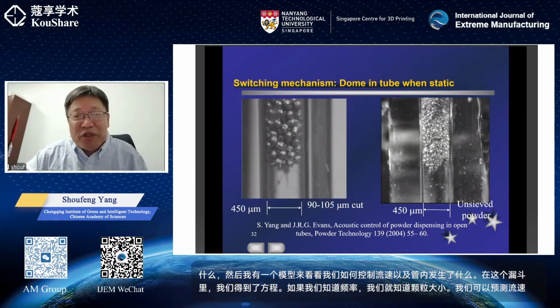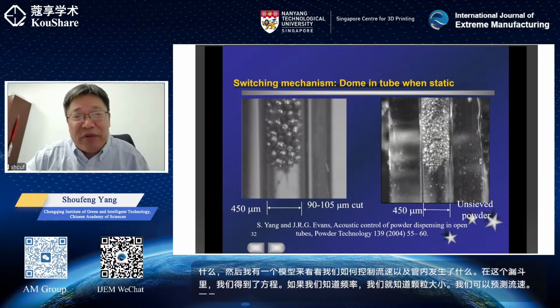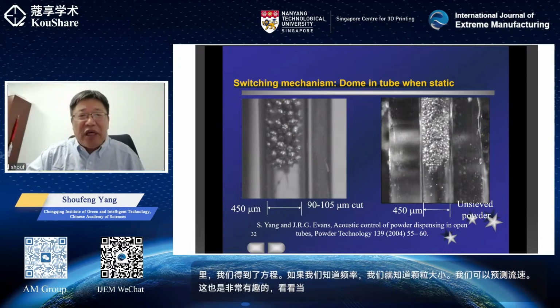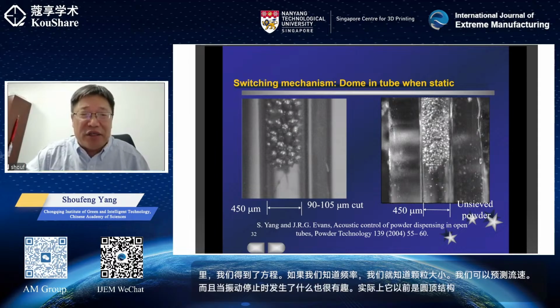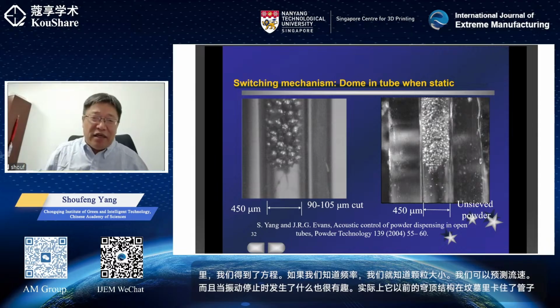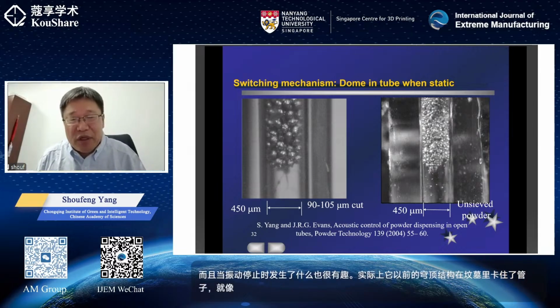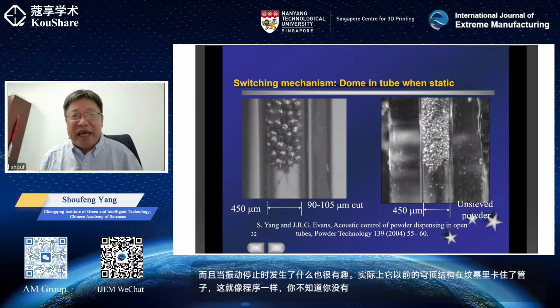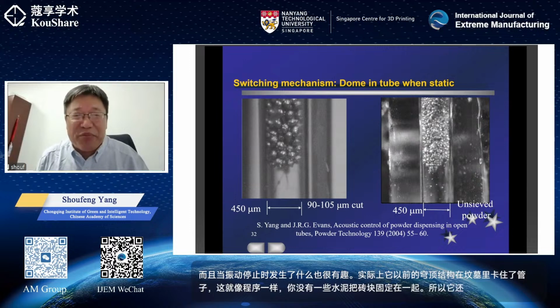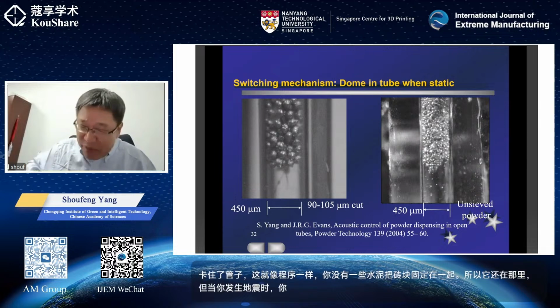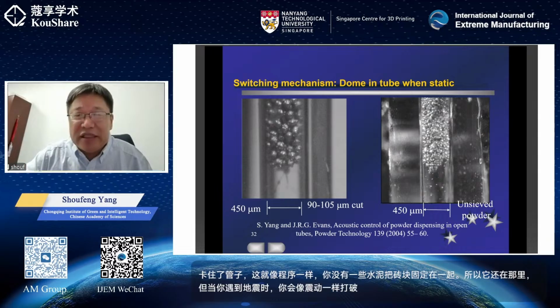And also, it's very interesting to see what happened when the vibration stops. Actually, it forms a dome structure inside the tube, stuck in the tube. It's like a procedural dome. You don't have some cement to hold the bricks together, so it stays there. But when you have some earthquake, you break the dome. So like a vibration, we break the dome structure inside the small tube.